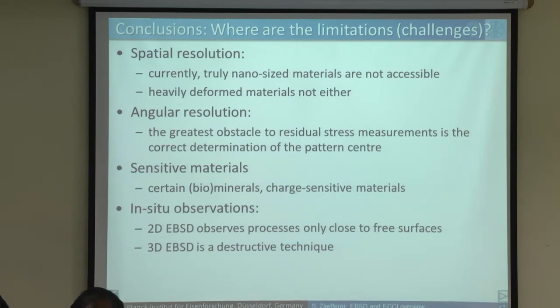It is, however, of course, cut. The nucleus structure is destroyed. So the nucleus on a surface will behave very differently from a nucleus inside of a material, undestroyed. If you make conclusions out of a 2D in situ observation, then also imagine a deformation experiment. You have no stress on the free surface. It's very different from a stress from a constrained sample, from a constrained grain inside of the material. So if you want to make conclusions from that, you must be very careful. It's only 2D observations with respect to 3D bulk.